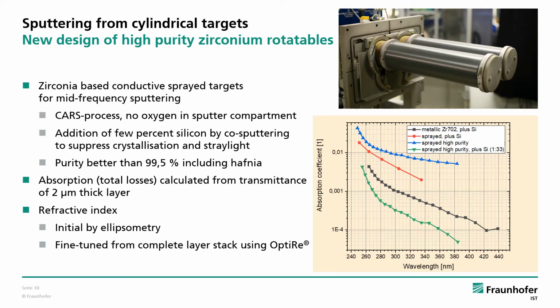For comparison, you see absorption results from different targets on the right. Actually, these are the total losses that are calculated from the transmittance of 2 micron thick layers. The black curve is from a metallic target from standard material ZR702 in pure metal mode. Even the addition of quite a lot of silicon did not help to get as low losses as needed for 80% transmittance at around 300 nanometers. Another spray target without focus on low impurities had even worse values, as can be seen in the red line.